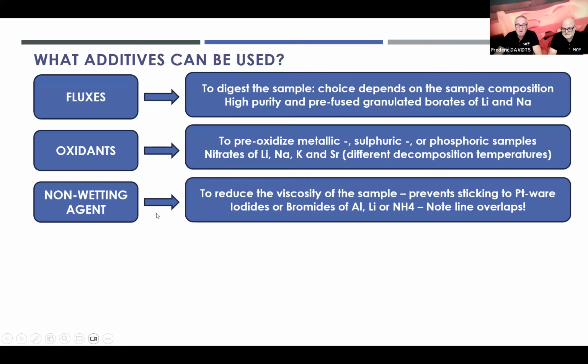Non-wetting agents are also important because these reduce the viscosity of the sample and prevent sticking to the platinum ware. If you wouldn't use those non-wetting agents, your platinum ware would be completely dirty. It makes it more difficult to clean it. And in general, those are iodides or bromides of aluminium, lithium, and ammonium.